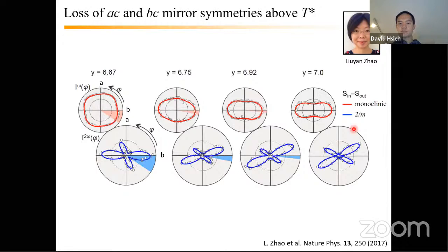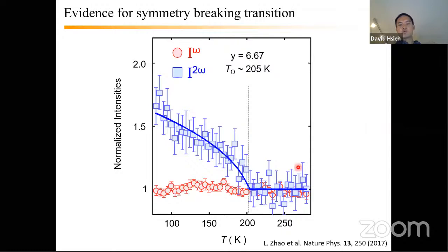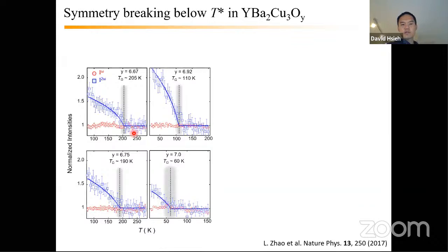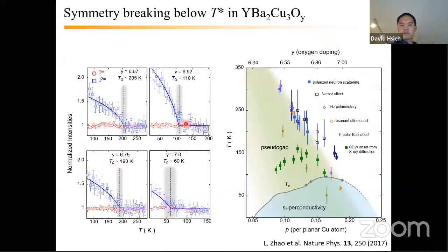Okay, so this is already present at high temperatures above T star. And as we cool below T star, you see that, again, in the linear response, there's nothing remarkable happening, but there is this uptick in SHG intensity, reminiscent of some of the data I showed you earlier on other compounds. And you can follow this onset as a function of doping. And what you find is that this onset temperature is changing in a way that nicely falls along the T star line that's been identified by these various previous measurements, okay?